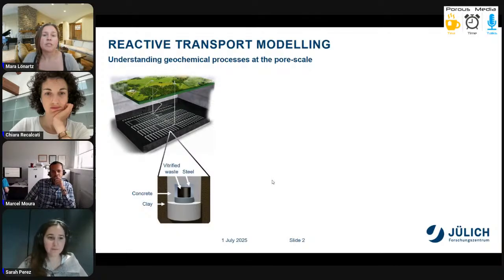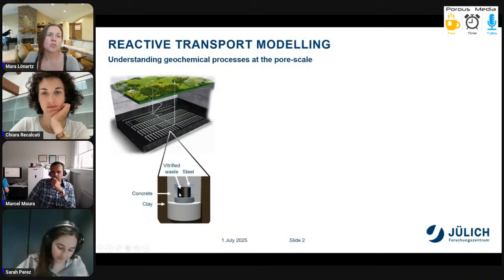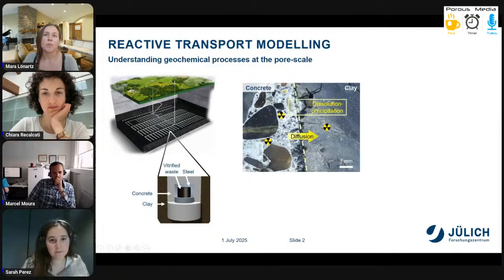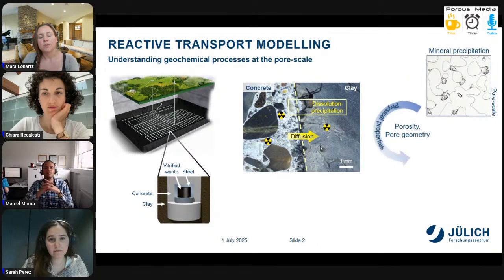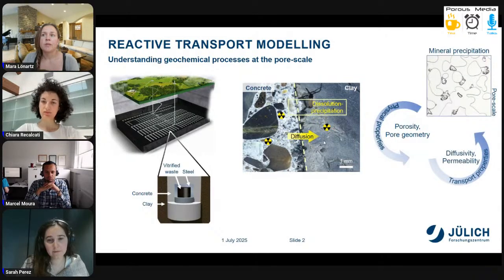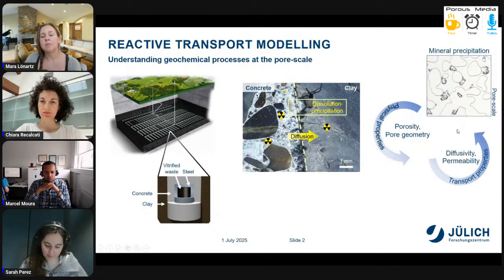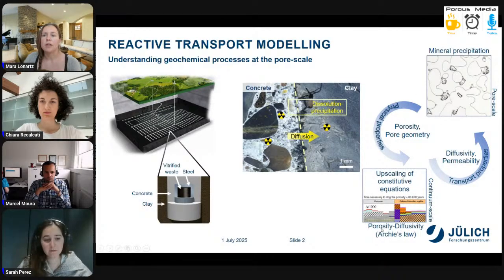As you might know, several countries are relying on a multi-barrier system, which confines the vitrified waste surrounded by a steel canister, concrete, and a host rock, here for example clay rock. Especially at the interfaces of these materials, chemical and thermal gradients promote the dissolution and precipitation of mineral phases, which in turn change our pore geometry and reduce the porosity, and with this also the transport properties of our porous medium, like the diffusivity and permeability. In the case of mineral precipitation reactions, continuum scale models usually couple the diffusivity and porosity using the so-called Archie's law and predict the case of clogging as a final state, occurring in this example after 10,000 years.